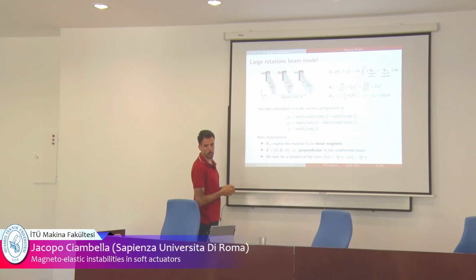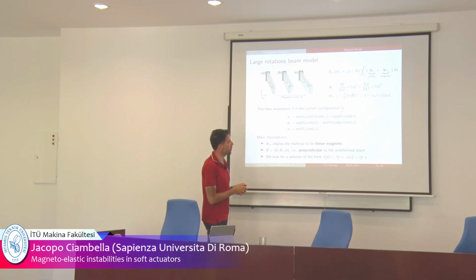the curvature squared, plus the derivative of the twisting angle squared. So you have 2 degrees of freedom, theta and phi. And this is the abscissa along the beam length. On top of this, you also have magnetic energy. And as I said before, because the field is uniform, the only term in the magnetic energy is the one that weighs the mutual orientation between the particle at position S and the magnetic field, B. Okay? And so the total energy is the sum of these two.